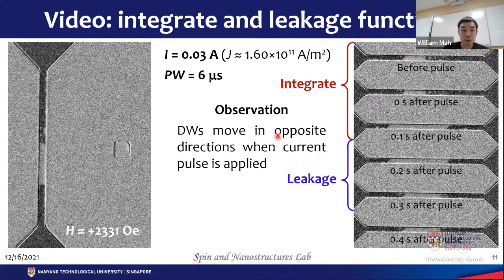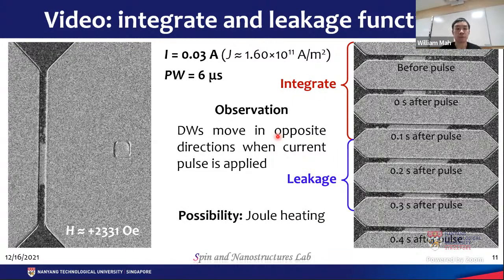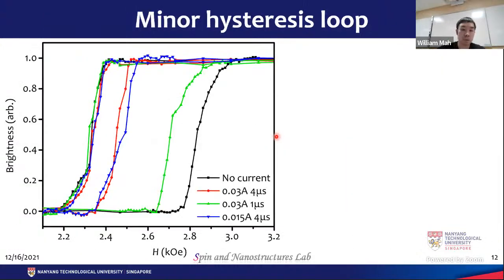So one possibility is that this is due to Joule heating. But in order to determine if Joule heating is dominant or has any significant effect or not, we did some minor loop measurements. This black curve is the reference case. It's the field-only case. The rest have current pulses, and the details of these current pulses are here in the legend.